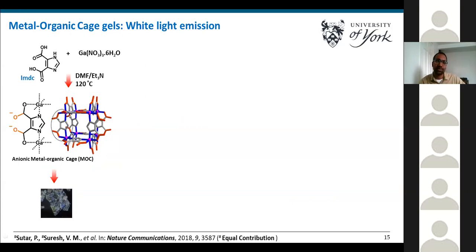So for creating the white light emission, we use a gel-like system to have better processability. So here we used anionic metal organic cages as starting materials, which are prepared from gallium nitrate and imidazole dicarboxylic acid. I call this imidazole dicarboxylic acid linker IMDC for ease later on. So here, each IMDC chelates 2 gallium centers through nitrogen and 1 oxygen of the carboxylate, leaving the other oxygen free, and it is negatively charged. So the whole metal organic cage is extremely negatively charged because of the leftover oxygen negative ions.